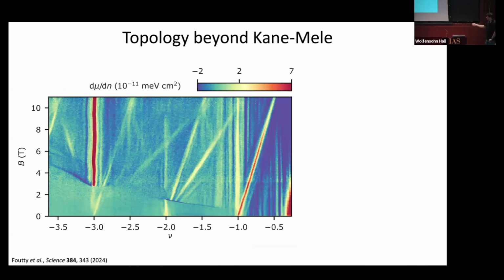Previously we were looking just at this low field region of the phase diagram. Again, as we increase the magnetic field further, you can see that in this high field limit, there are tons of Hofstadter states which are appearing. So this is really generic. If you're able to probe clean enough systems, these Hofstadter states, even in transition metal dichalcogenides, appear. And again, you can pick out by eye that there is a transition that separates distinct behaviors, where one behavior is favored at high field.